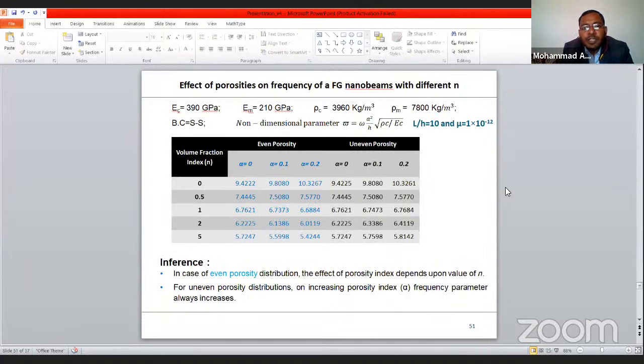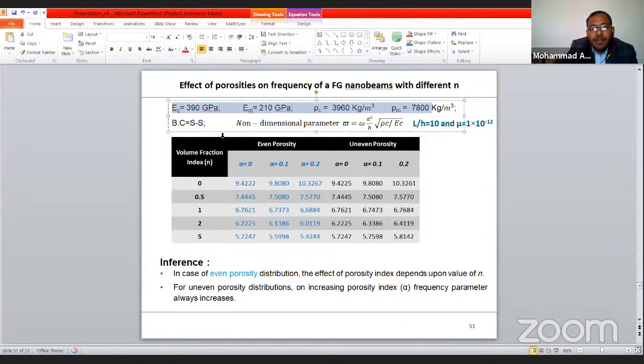Here, the effect of porosity on the frequency response of the functionally graded nano beam with different values of volume fraction index n. Here, the material properties of the ceramic and metal are given here, and the boundary condition is simply supported. And in this case, the L by H ratio, that is length to thickness ratio, is 10, and mu, that is non-local parameter, is considered to be 1 into 10 to the power minus 12.